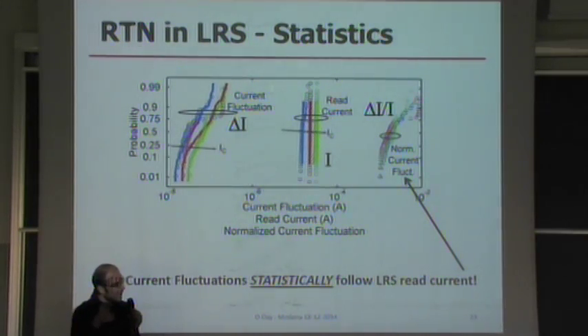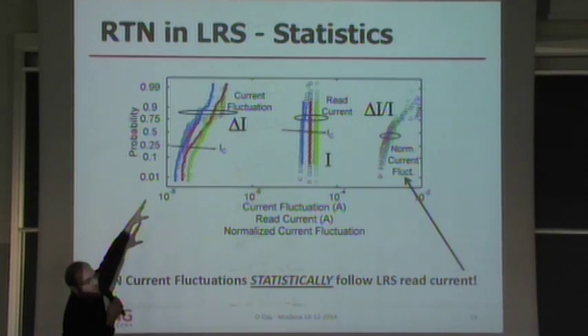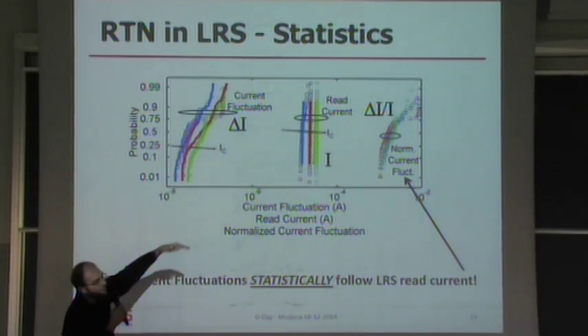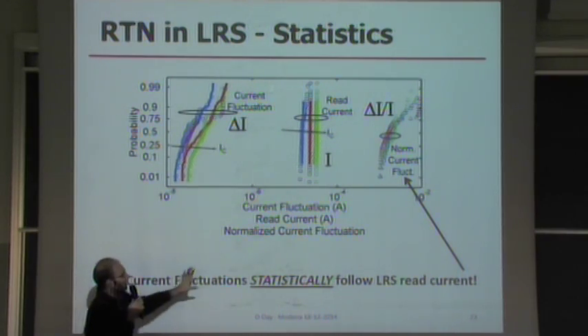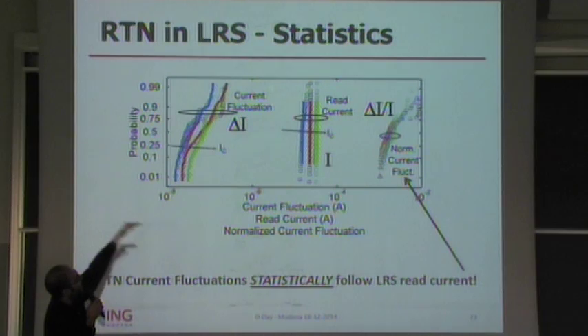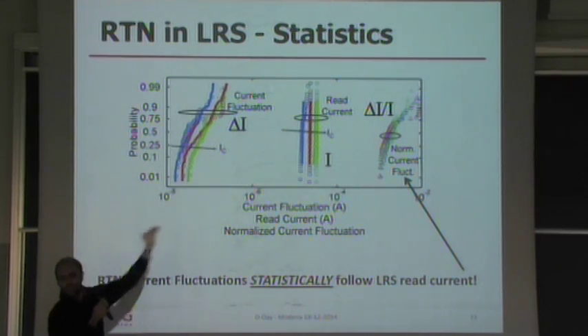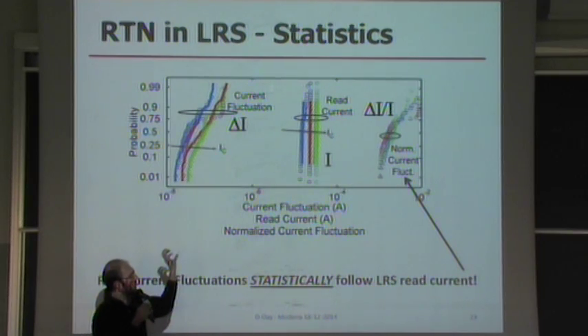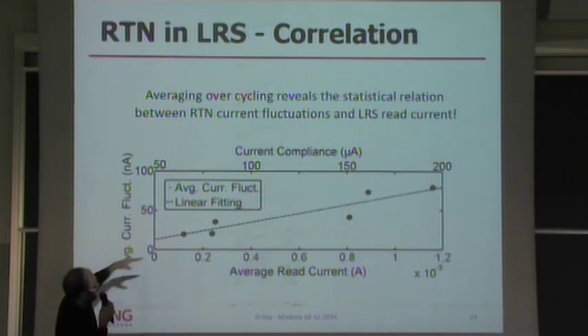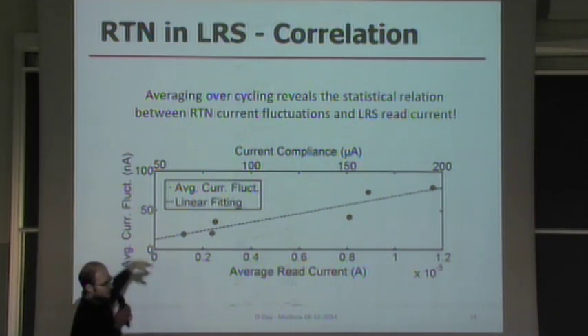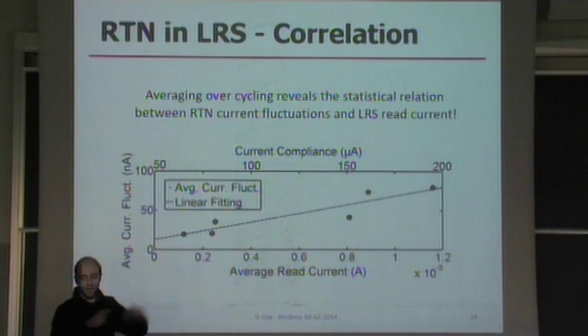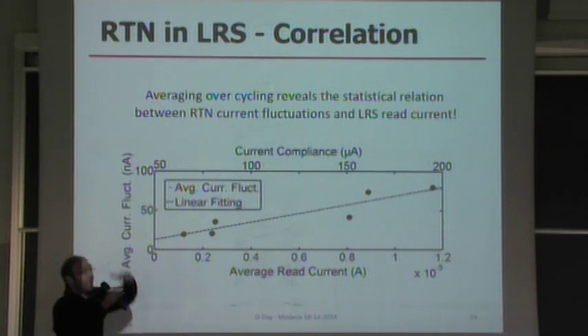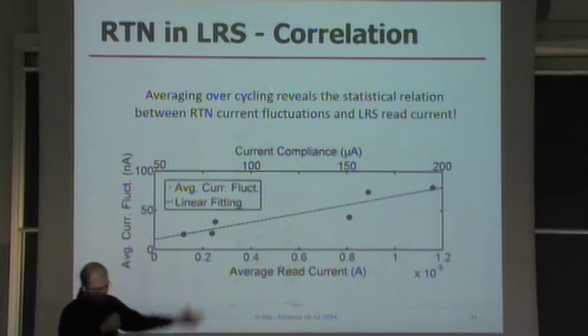And we did the same thing in LRS, and as you can see, we can now modulate LRS not with the reset condition, but with the current compliance. And as we can see, there is the same statistical relation between the reading current and the current fluctuation. Delta I over I is always fixed there, which means the RTN fluctuation statistically follows the read current. And we can see this linear statistical relation here. The average current fluctuation and the average read current are linear, and they follow the current compliance. Higher current compliance, thicker filament, lower resistance, higher reading current in the same condition, larger current fluctuation. That's the message of this chart.